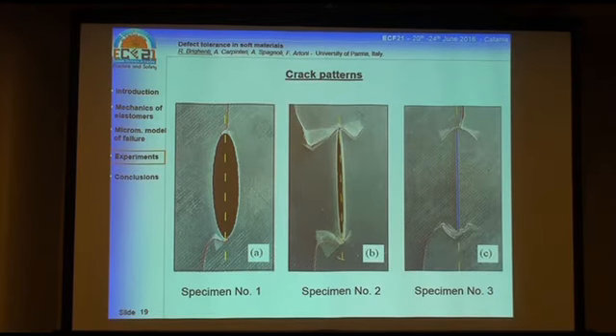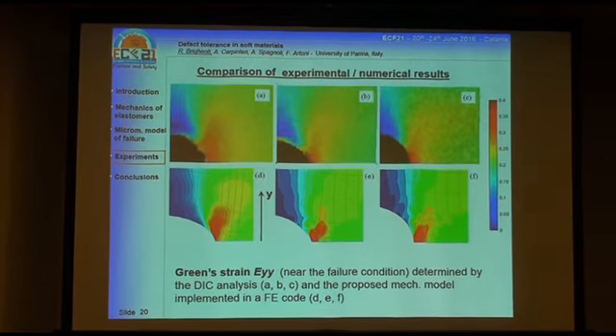So the initial defect is really unimportant in these cases because we have this local failure of chains close to the crack tip, while after, let's say, a local failure, we have a behavior which is almost independent of the defect that we have initially in the specimen. And finally, here I compare the result from the DIC measurement to those coming from the continuum model I showed before, that has been implemented in a nonlinear finite element code. And you can see the comparison of the strain, of the green strain, for the three different cases of blunt, mild, and perfect crack at a given level, of course, of remote strain.